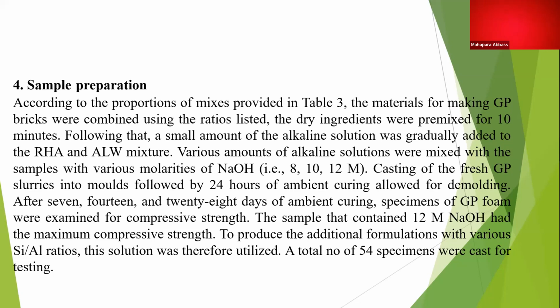For the preparation of specimens, all the dry ingredients were mixed together, and then the liquid part, which was the blend of sodium hydroxide, sodium silicate and some water, was mixed with the dry ingredients in two halves. The first half is added and mixed, and then the second half was added. Then it was thoroughly mixed again till the mixture became homogeneous. Then the molds were cast. A total of 54 specimens were cast. Ambient curing conditions were followed. There was no water curing; all the specimens were cured in air.